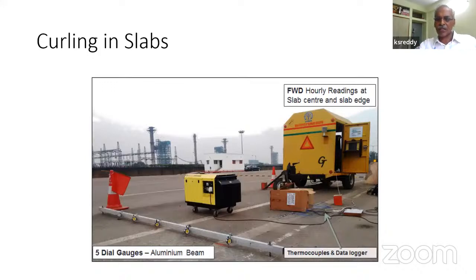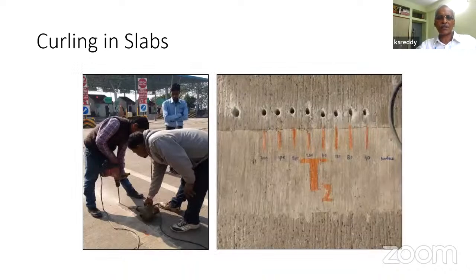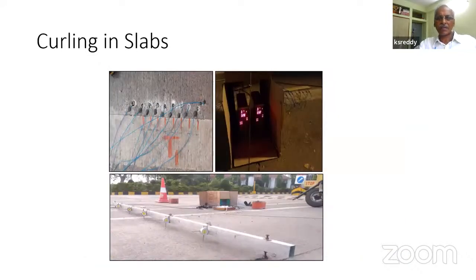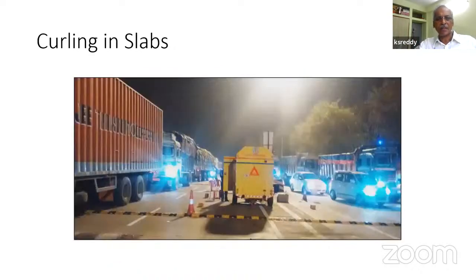See whether the slabs actually curl or not. How much of the slab curling is actually restrained by the self-weight of the slab? We were making some experiments on National Highway 60. This is the Kharagpur Palasur bypass road. We put dial gauges here. We had a frame which was measuring the vertical profile of the slab. We were also trying to measure the temperatures of the slab at different depths so as to get the temperature profile, temperature gradient. And then simultaneously we were measuring the temperature profile and also the lifting up and down of the slab.